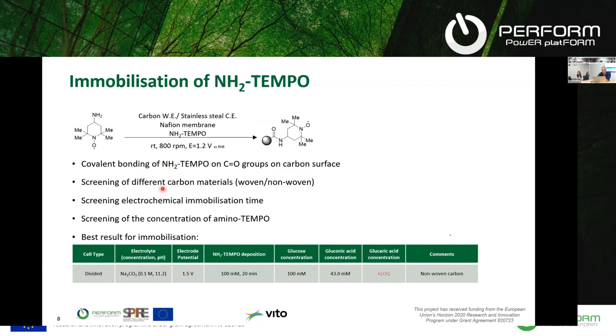In fact, we tried different types of carbon materials, electrochemical immobilization time, and also concentration of amino tempo. But the best result we got was only capable of really converting glucose to gluconic acid. So the first oxidation step, basically. No glucaric acid was found.